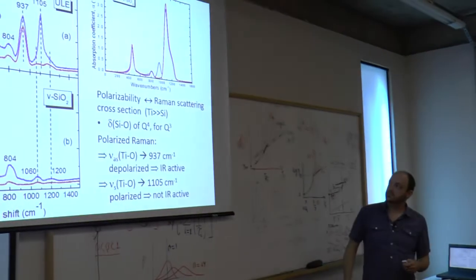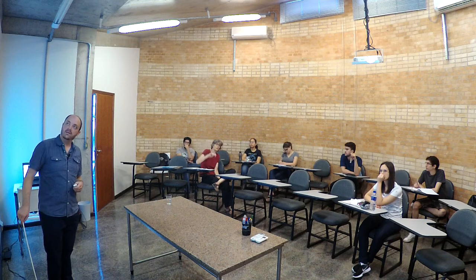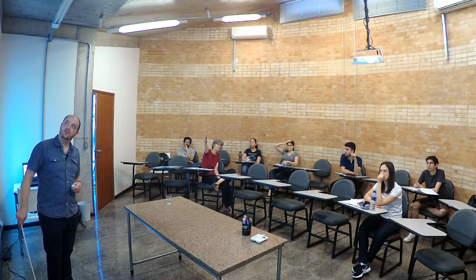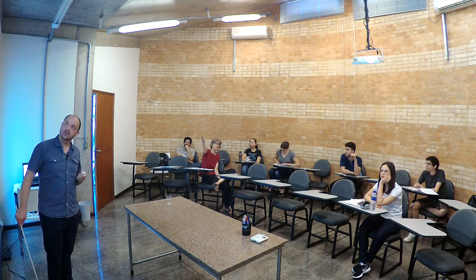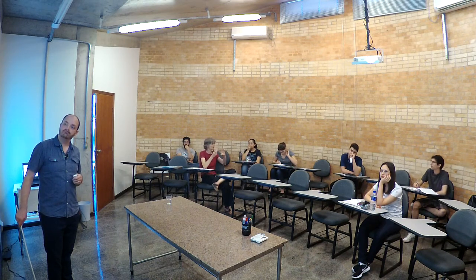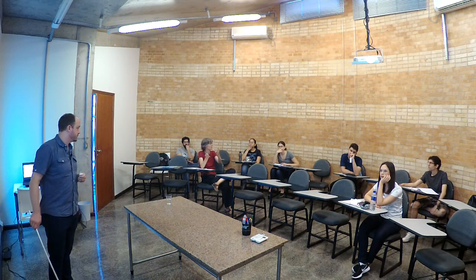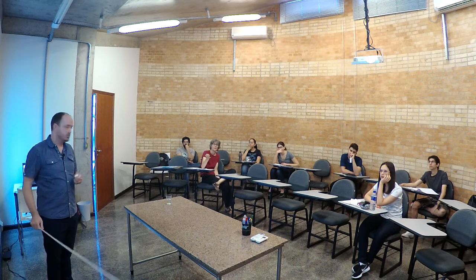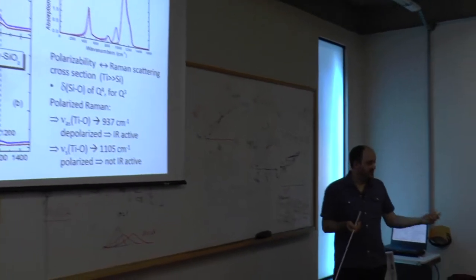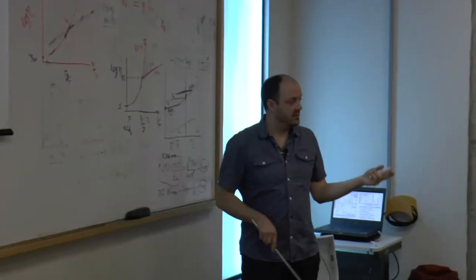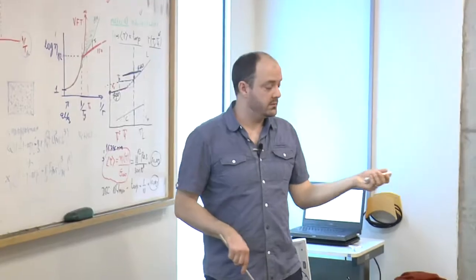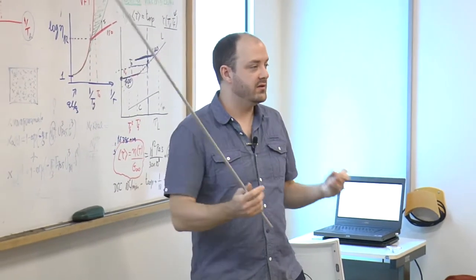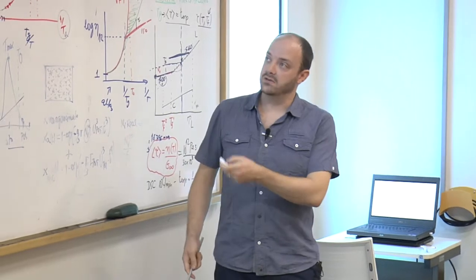Do you show the infrared spectrum? Because they don't stick out in the infrared. I show the absorption coefficient. This? Yes. So you don't see much difference. Yes, there is a difference with the titanium band, but in the infrared you see there's no sign of Q3 units. So in both the titanium-doped and the SiO2 glass, you see the typical infrared spectrum of Q4 groups. So this is a nice example where Raman and infrared complement each other, and in the classes after we do the experiments, Doris is going to go through many more examples where we have all the different spectroscopic techniques joined together. So that's a nice one.